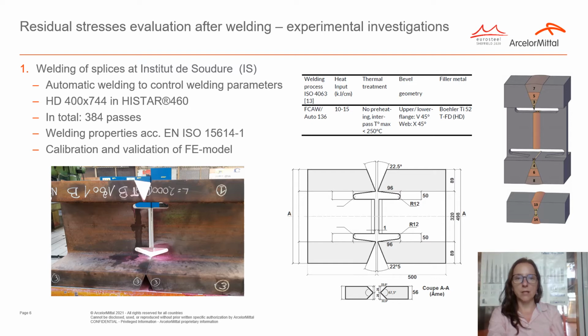and the lower flanges and, at the second stage, the web, in order to avoid additional constraints in the connection. The reason for performing automatic welding was to better control the welding parameters that are presented in the top middle table. In total, 384 passes were used, and the preparation of the profiles before the welding is presented in the bottom right image, and the geometry of the cope hole is according to AWS design code recommendations.